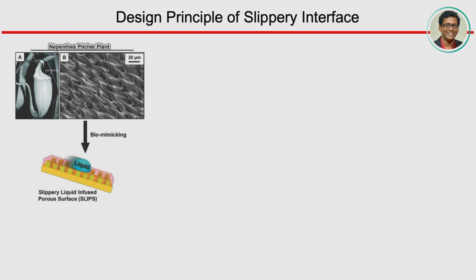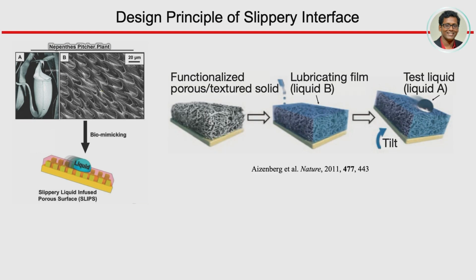Once the insect lands there, it slips into this pocket, right? In that particular design, you have this kind of topography, and the lubricant is filled in there, which makes this interface extremely slippery. Inspired by that, Joanna Aizenberg and her team took a porous and functionalized coating and lubricated it with Krytox, which is fluorinated, and this substrate is also derived from fluorinated molecules. Once you put a probe liquid, water or oil, it started sliding.